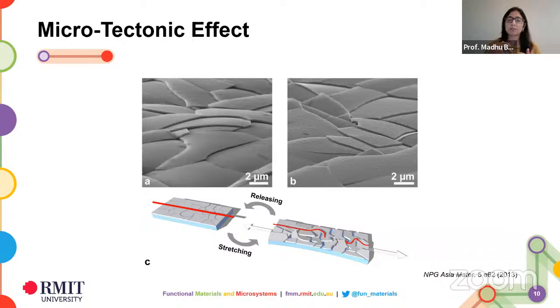So the indium tin oxide material looks like overlapping plates, which are sitting on top of each other. And then once you look at it, you realize intuitively what's happening when you apply strain. When you're applying strain, you have the plates sliding apart from each other, but still maintaining electrical contact. But when you apply too much strain and they lose the electrical contact, that's when you lose the performance. But then once you let go of it, once again, they slide back on each other, and you get back to your original state in some sense. So this is the reason you're able to apply strain up to around, say, 12 or 15% and still maintain the electrical contact and the performance of these materials.